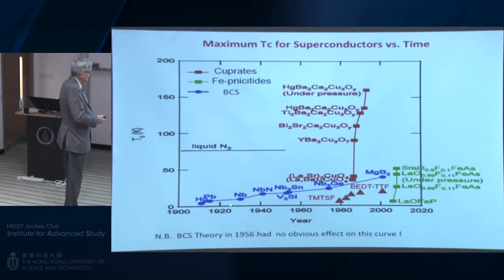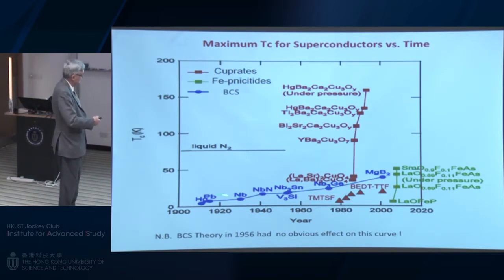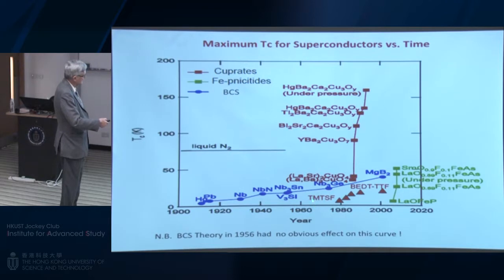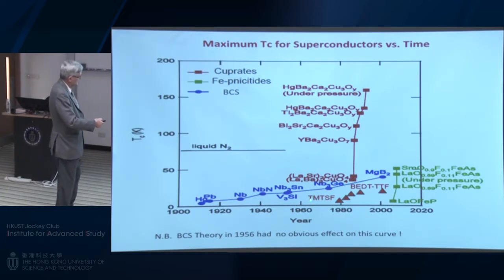So in fact, if we look at the plot of the maximum of TC as a function of time, these blue ones here are the electron-phonon BCS-like superconductors. And I was talking about 1957 here, you see. Well, no big effect. The discovery of the explanation, the microscopic theory, did not have a big impact on TC. It rose very slowly. This is where, as Vic pointed out, many years ago when I started in condensed matter physics, you see nothing much happened. So people were very pessimistic because there didn't look like any action in this curve for many years.